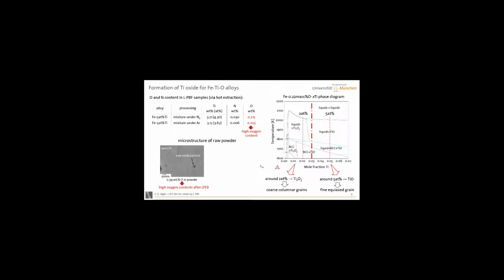The question is, why do we have TiO in the case of 5% titanium, but not in the case of 2% titanium? And thermodynamics can give us an answer to that. We just plugged the numbers into Thermo-Calc. So we added this 0.2% oxygen that we measured in the as-produced samples, plus X% titanium. And here on the right-hand side, you see that if you have less than approximately 3 atomic percent titanium, Thermo-Calc predicts Ti2O3, which is exactly what we see for the 2% alloy. And then at higher concentrations of titanium, Thermo-Calc predicts TiO. So the thermodynamic predictions fit reality very well. That's always nice.